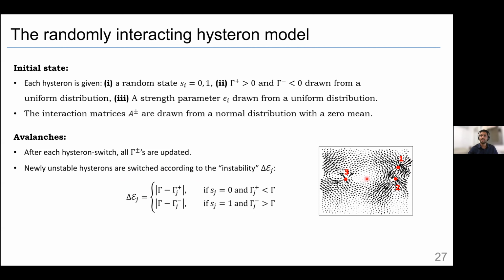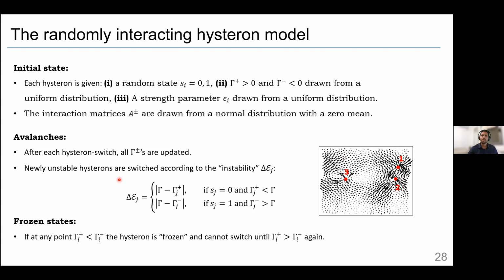So it can cause an avalanche, mainly 1 affects 2, which affects 3, and all switch at the same time. We also need to discuss what we call frozen states, which happen when gamma plus becomes lower than gamma minus. We call this hysteron frozen. It cannot switch until gamma plus becomes larger than gamma minus again.